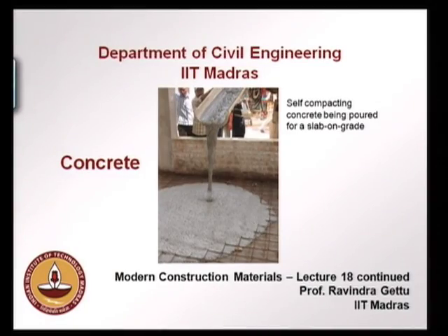In this picture we have a self compacting concrete being poured for a slab on grade, and if you have seen normal concrete and have not seen self compacting concrete, you would be surprised that concrete can flow as such. Here it is flowing almost a couple of meters in diameter and moving quite easily on a flat surface and through the reinforcement mesh. This is achieved by adding appropriate type and quantity of mineral admixtures as well as superplasticizers and viscosity modifying agents, which are chemical admixtures that we will discuss in a minute.